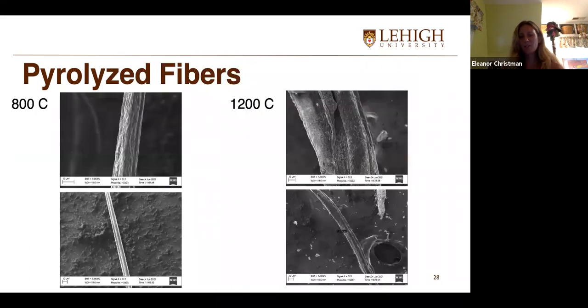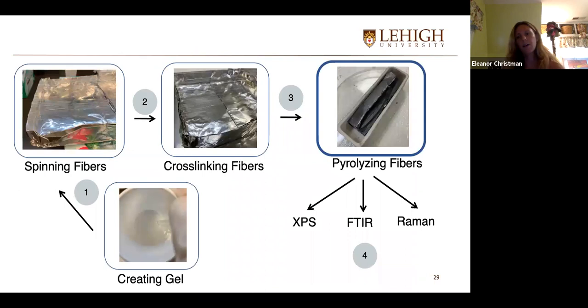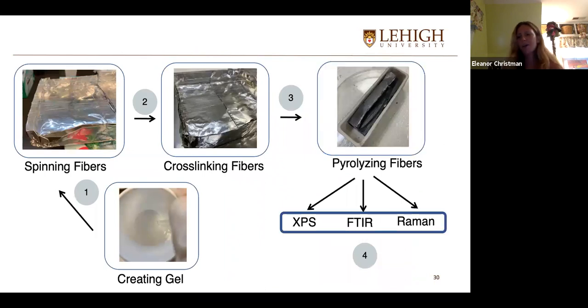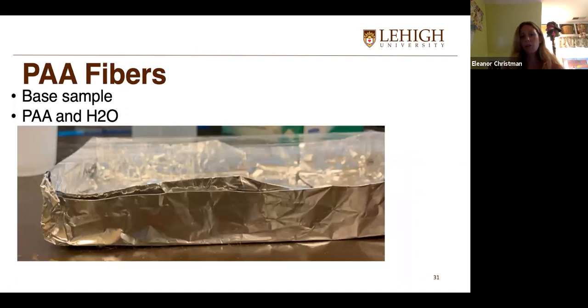And here are some images. I have the fibers at 800 here, and then the fibers at 1200. I took these images using the SEM. And then after pyrolysis, I can do a lot of different characterizations. I'll also note that I did make PAA fibers, which served as a sort of base sample, and I made those with just PAA and water.